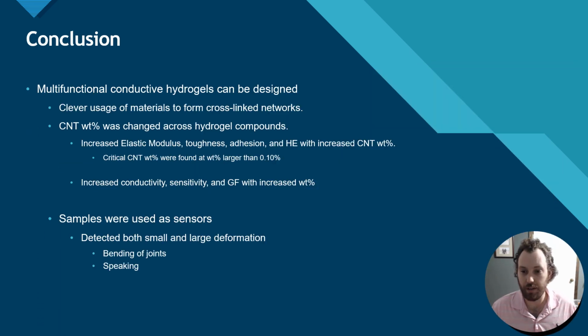In conclusion, we were able to show that it is possible to design a hydrogel with the different properties that we were looking for. Notably, we were also able to modulate these different properties via the carbon nanotube weight percent. We increased the elastic modulus, toughness, adhesion, and healing efficiency with an increase of the carbon nanotube weight percent. Interestingly enough, these four properties illustrated a critical carbon nanotube weight percent, which was found at weight percents larger than 0.1%. We also illustrated that an increase in carbon nanotube weight percent increased the conductivity, sensitivity, and the gauge factor, and did not show a critical weight percent. We then were able to illustrate that these samples could be used as sensors and were capable of detecting both small and large deformations, such as bending of joints and speaking.